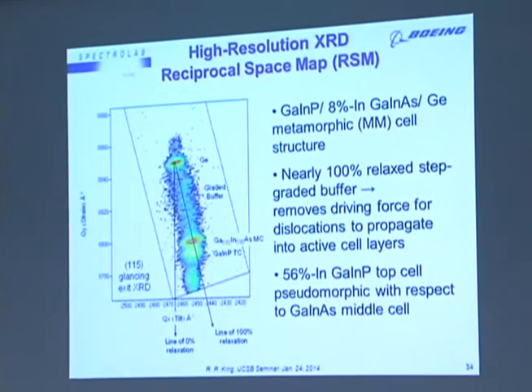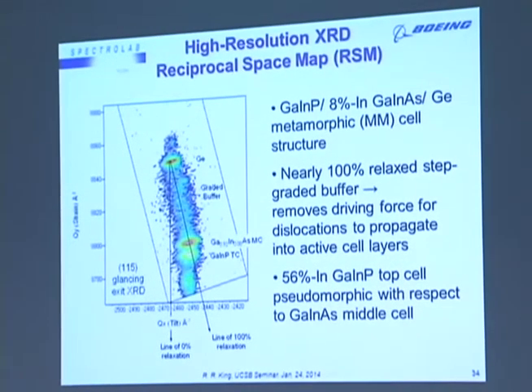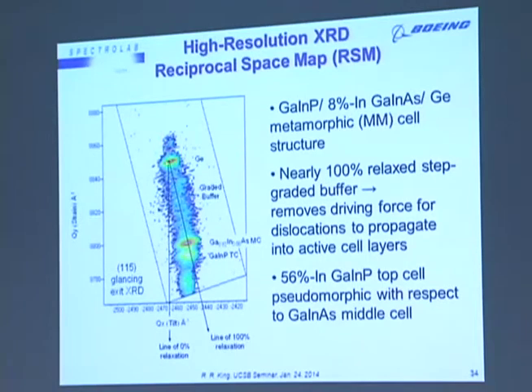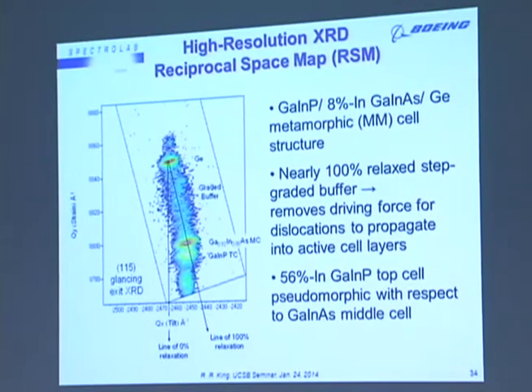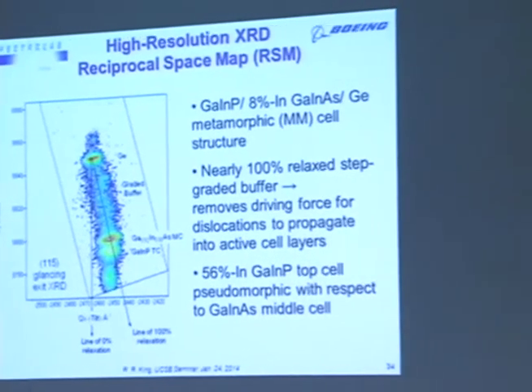Another way we can visualize the metamorphic structure is through X-ray diffraction reciprocal space mapping. There's the substrate, the germanium substrate is shown here. Here's our metamorphic buffer extending out to this new lattice constant of the gallium indium arsenide middle cell. And this buffer is designed to lie almost completely on the line of 100% relaxation. That 100% relaxed step-graded buffer removes the driving force for dislocations to propagate into the upper cell layers.